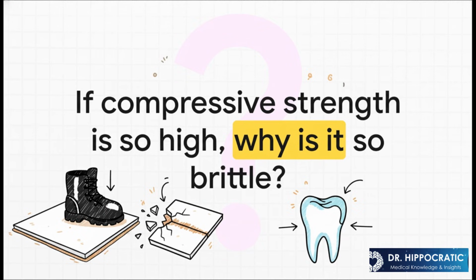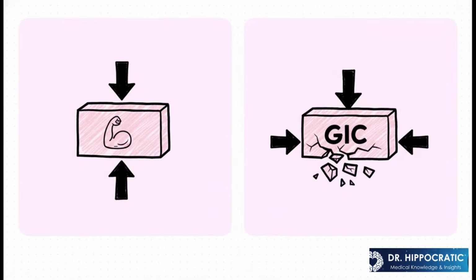Well, think about a ceramic floor tile. You can stand on it all day long. That's high compressive strength. But if you try to bend it, even just a little, what happens? It snaps. That's low flexural strength. GICs behave in almost the exact same way. And this slide spells it out plain and simple. Compressive strength is all about resisting being squeezed, and GICs are great at that. But flexural strength is about resisting bending or pulling, and that's where they really struggle. The problem is the ISO standard only measures compression, which just doesn't tell you the whole story of how it's going to perform in your mouth.